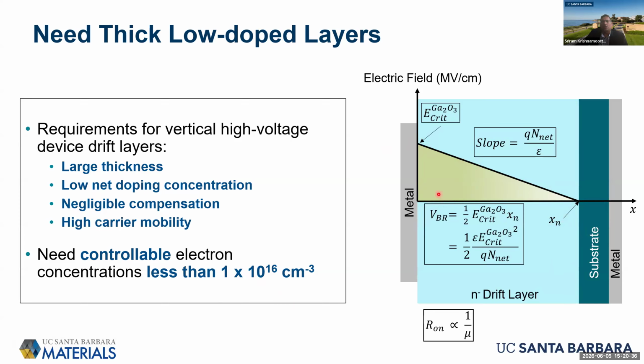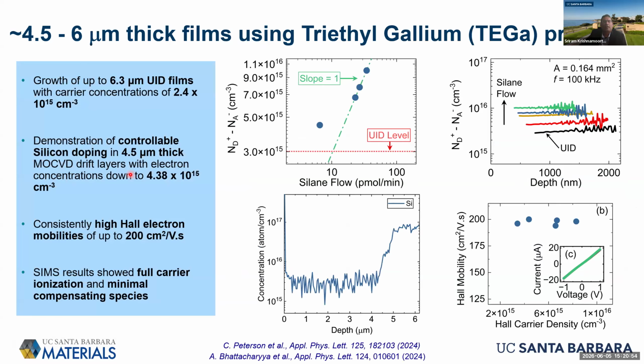So there is a need to develop techniques that can realize large thicknesses of these layers with low doping concentration, negligible compensation, and high carrier mobility in these structures. So we started some of this effort with MOCVD. This is some recent work where we've been able to grow 4 to 6 micron thick films. We've been able to reduce the unintentional background doping in the material to the low 10 to the 15s. And then by systematically varying the silane flow, we can control the doping in the film below a value of 1e16. So these are super pure, more than parts-per-billion pure films. We've been able to demonstrate that using MOCVD here at UCSB.